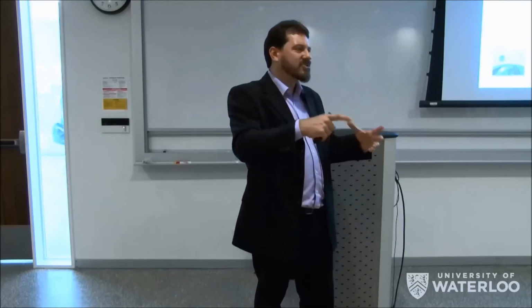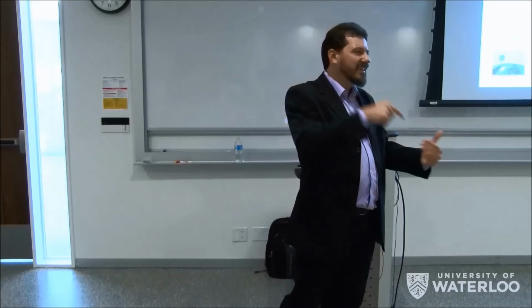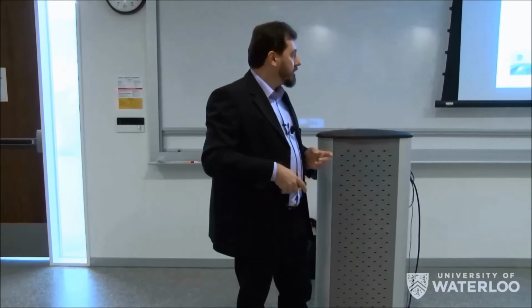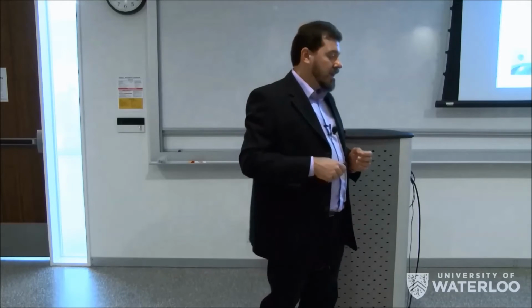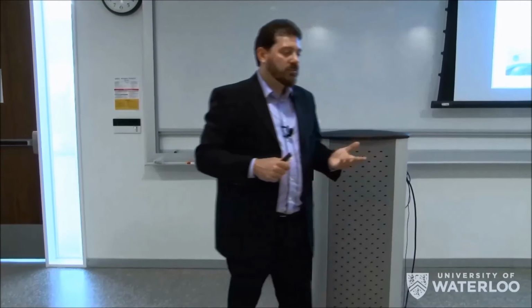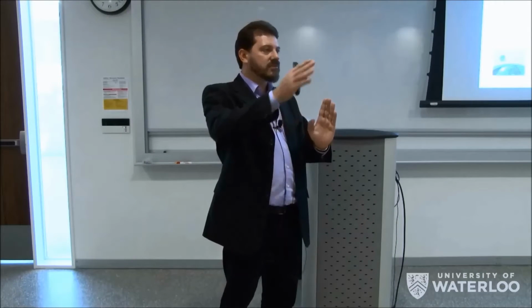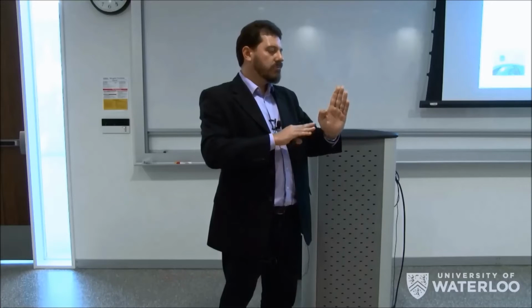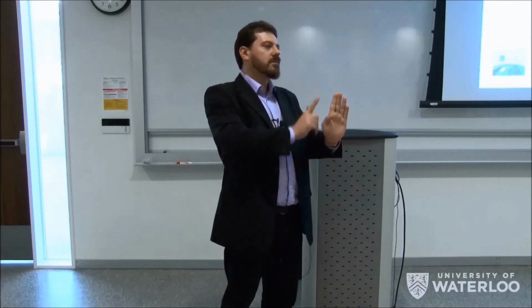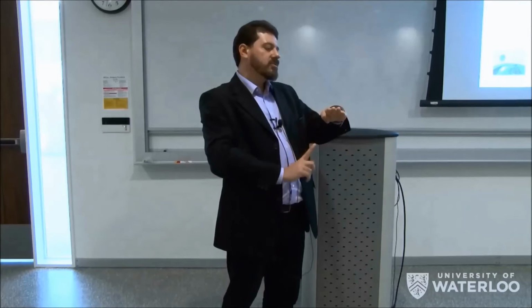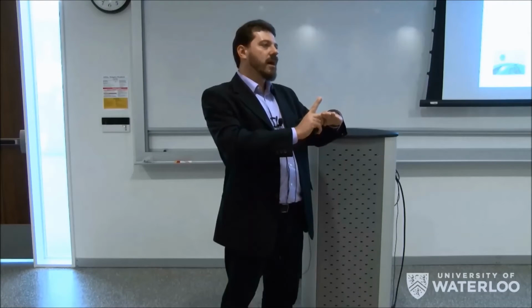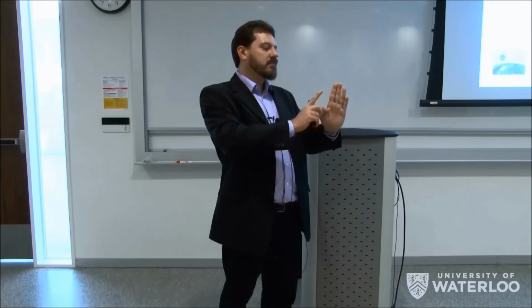It would be like a solid state, not STM, but when you do the AFM contacting there. One result I didn't show in detail is that from the transport measurement we could obtain the molecular orientation. We can get the dielectric constant of the system, and there is some theory work showing that the dielectric constant of copper phthalocyanine is about 13 along the molecule and 2.5 perpendicular. We actually got about 13. So it means that most of our transport might be along the molecule.